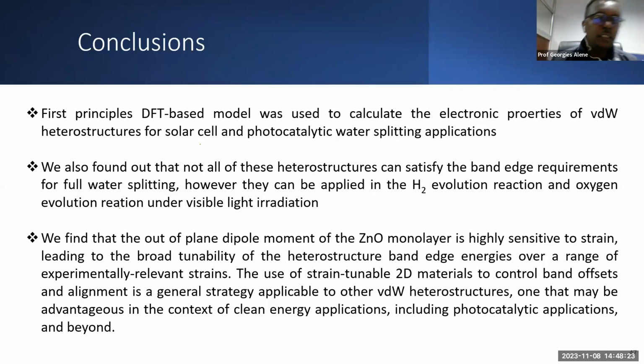So as a conclusion, we have used a first-principles DFT-based model to calculate the electronic properties of different van der Waals heterostructures. And we tested these heterostructures for solar cell and photocatalytic water splitting application. Our results show that not all of these heterostructures can satisfy the band edge requirements for overall water splitting, but they can be used separately for the oxygen evolution reaction and hydrogen evolution reaction.